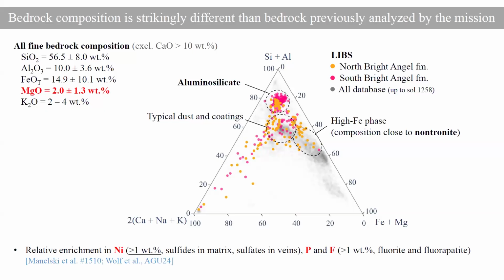Instead of mafic rocks, what we see here is a bedrock mostly enriched in some aluminosilicate phase. But we do also have some scatter, with a few measurements of more iron-rich phases that have a stoichiometry close to nontronite. We see some scatter around our typical dust and coatings compositions. And we also have some scatter toward the alkali apex, which I'll come back to in a minute.